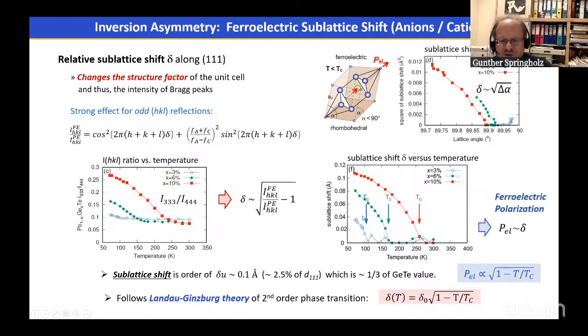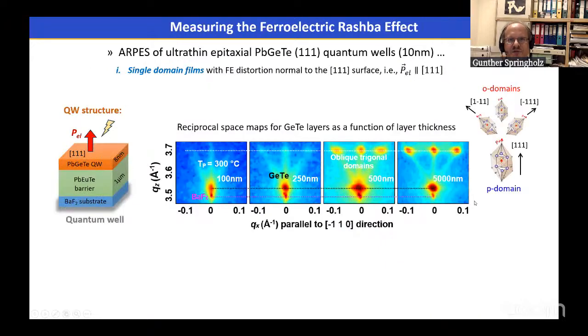And the result is shown here on the lower right-hand side. So we can quantify the sublattice shift as a function of temperature, and this follows nicely Ginzburg-Landau theory of second-order phase transition, where the sublattice shift as a function of temperature is a constant times the square root of 1 minus T over Tc. And with this sublattice shift, we know that the electric polarization is proportional to it, because the sublattice shift times the ionic charge of the anions and cations gives directly the electric polarization of the system.